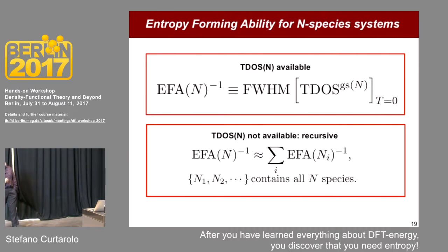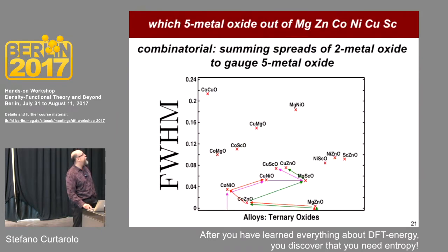I say that if the thermodynamic density of states is not available, I sum the thermodynamic density of states like the Kirchhoff sum. Why? Because if you have a thermodynamic density of states for AB, and then you have a thermodynamic density of states for AC, remember that C can become B, so there is a convolution between the thermodynamic density of states of AB and of AC, and the FWHM tends to get narrower. So if you do dimensional analysis, you discover that this is the only logical ansatz that you can give to the pseudo entropy, this entropy forming ability, which gives you extensivity with respect to the number of states. Okay, so this is pretty much a hopeful ansatz. Okay, now the question is, I'm going to skip these slides on details, right? Okay, actually no, it's okay.